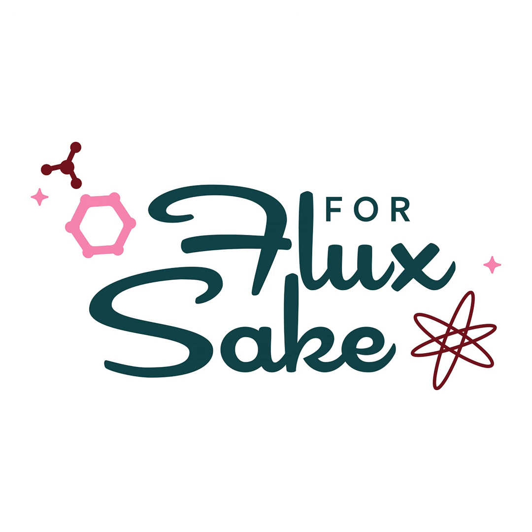And so the real question is where is its position on its firing curve? The amazing thing you see when you look at these firing profiles that we've done is we fire a body at every single temperature, and we literally can watch it vitrify. And what I can say definitively is every single body will vitrify. Does it vitrify at the temperature it's being advertised at? That's a different conversation. A lot of the times, my big problem with cone 6 or mid temperature is that the bodies are under their position, which means that they are on the curve up, but they have not hit the window where they are actually vitrified.